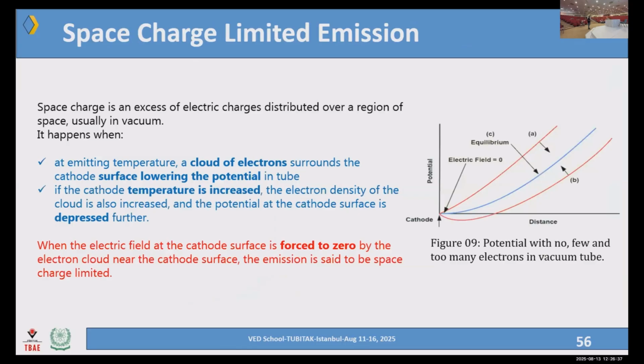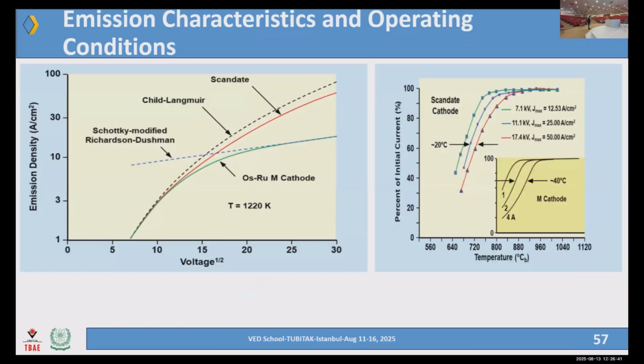Okay, we have gone through this potential thing already, but let me show you this. The emission density varies with different types of cathodes. For example, osmium, you recall the table which I showed a few slides back, osmium, ruthenium can be coated on this, so the efficiency is different, the temperature and time are different. And if you operate your cathode at higher temperatures, it's very convincing that you get very high amps per centimeter squared, but your life is compromised. The percentage of current is there, but the life goes away very quickly.